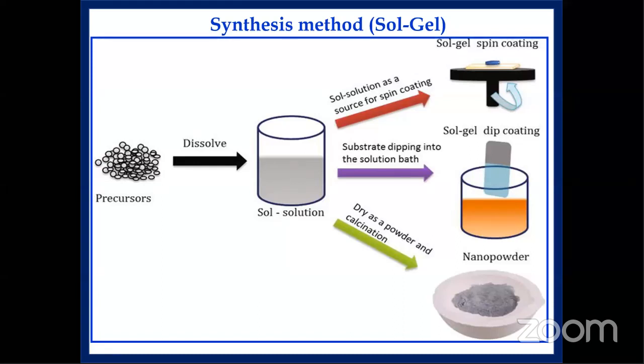If you want to prepare a film, you can use the solution. This is a colloidal solution, and you can immerse a substrate like glass or aluminum foil in it, with heating. Then you can prepare the film by the dip coating method. This is the sol-gel dip coating method, and you can also prepare thin film by using spin coating. So with the sol-gel method, you can prepare both powder and film.